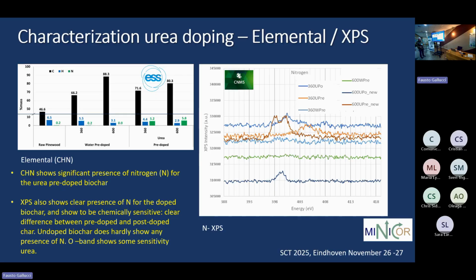If we look at the properties of this biochar, for raw pine wood we have very little nitrogen. This is raw, and this is soaked in water and dried without any nitrogen. It's very low, and then we dope with urea. We see that we get interesting levels of nitrogen inside, around 5 to 6%, at both the low temperature and the high temperature in our investigations.